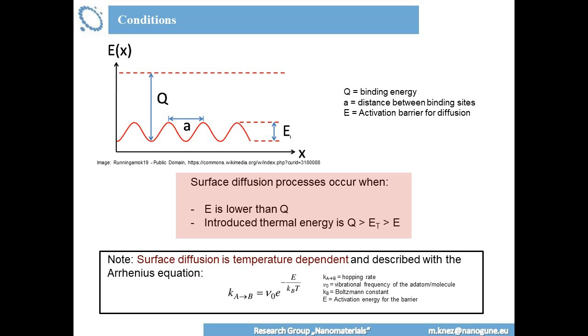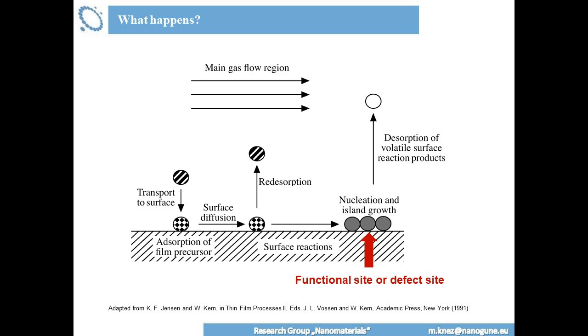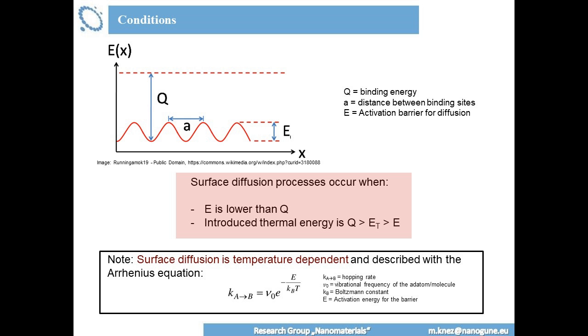In ALD, this is typically not the case. You operate at temperatures from room temperature to 100, 200 degrees. That means you are in a regime where those molecules which attach to the surface are starting to diffuse and to move around, and then they either desorb or not, or they bind. And this depends on this graph here, just as a rough idea to give you an idea of what it looks like. So if you are operating in a temperature regime, giving this thermal energy, above the activation limit of hopping events from point A to point B, but below the energy which you need for desorption of the atom or the molecule, then you will have this diffusion, and this diffusion will lead to a condensation or binding of the molecules to defect sites, and then starting to nucleate and grow islands or whatever on defect sites.